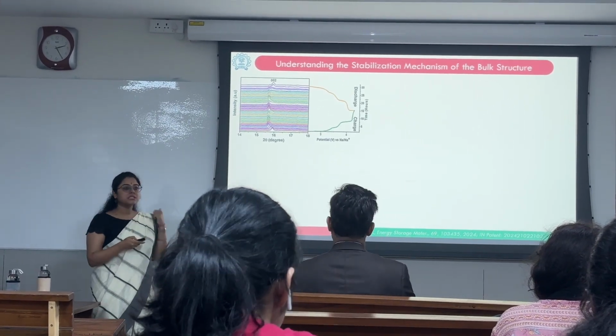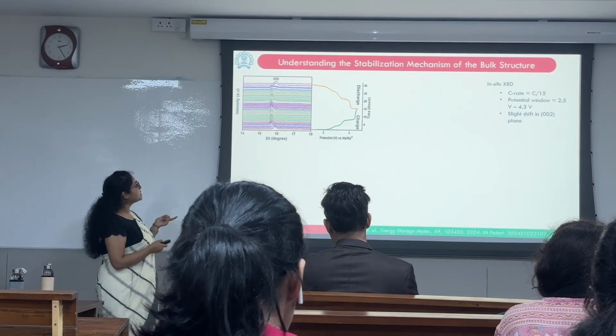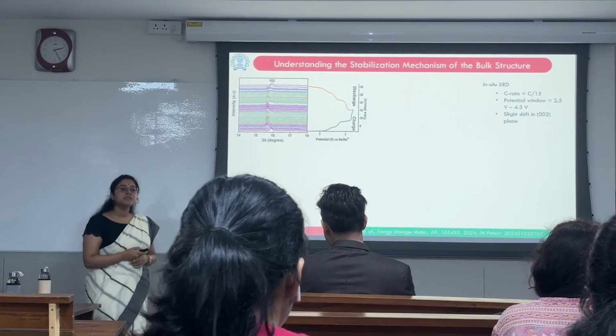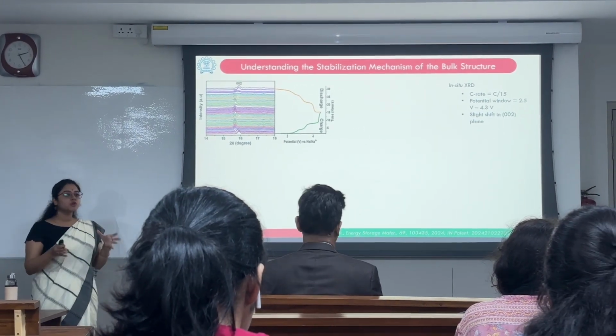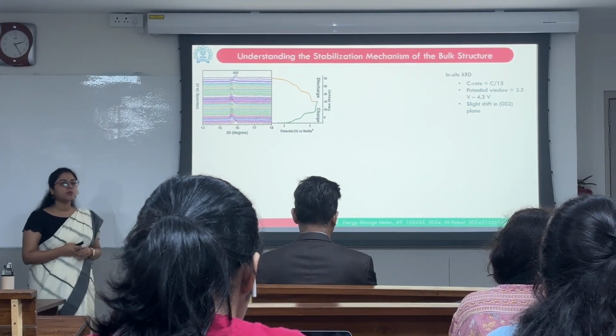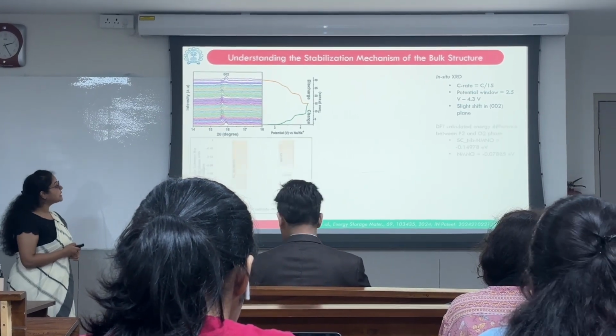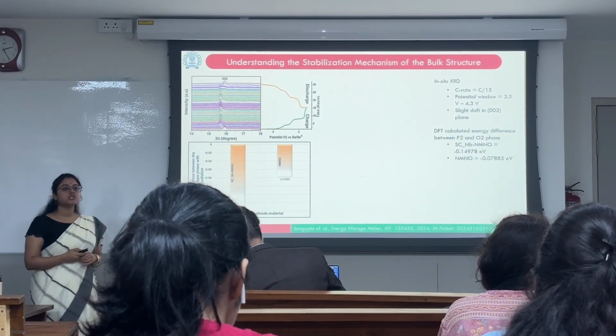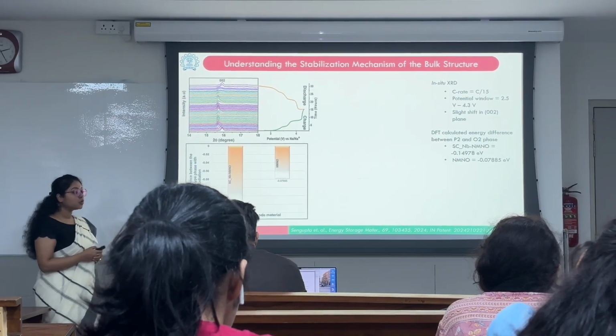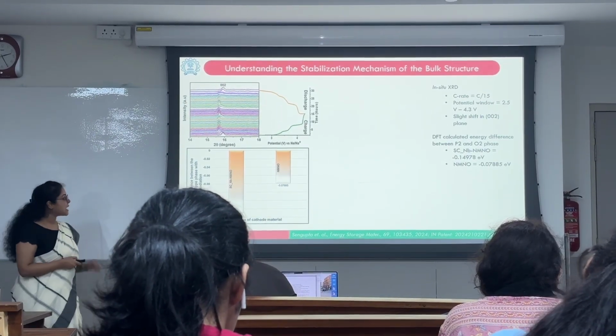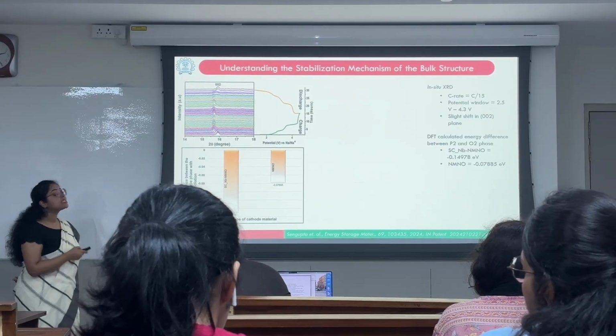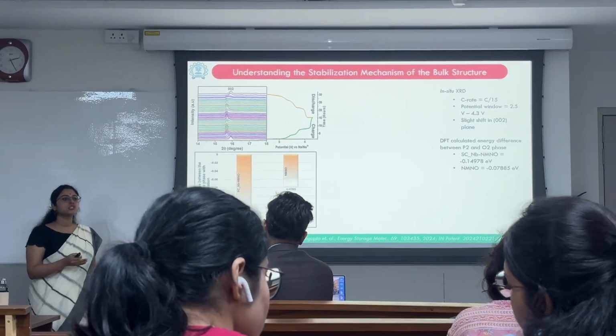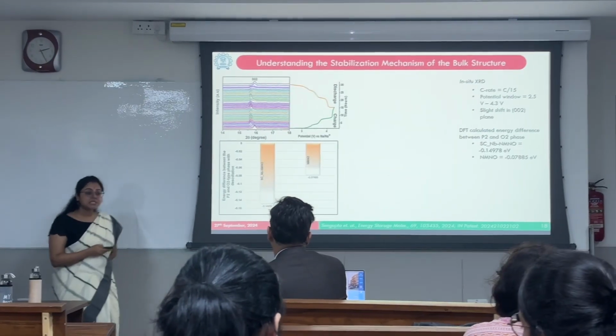So in order to have the accuracy, we did the cycling at a very slow rate of C by 15 and utilized the full potential window of 2.5 to 4.3 volts. This was also validated through the energy difference calculation between the P2 phase formation and the O2 phase formation, which shows that the niobium doped NMNO is less susceptible to phase transition in comparison to that of the pristine one.